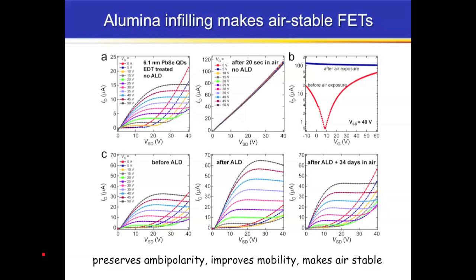We've also applied the ALD technique to show that we can improve both the stability and the charge transport parameters. So this is a graph here that shows what happens to a film without ALD. We have very nice ambipolar conduction before air exposure. That's after air exposure, it really goes to pot.